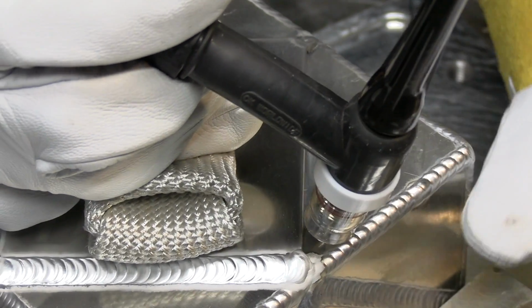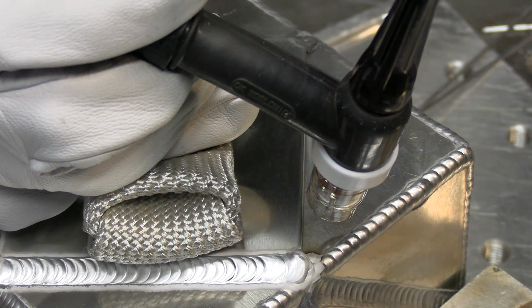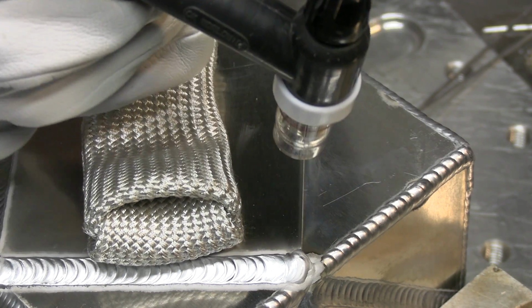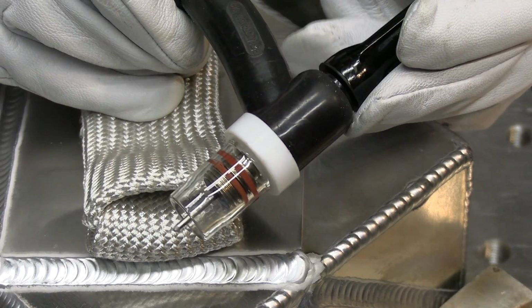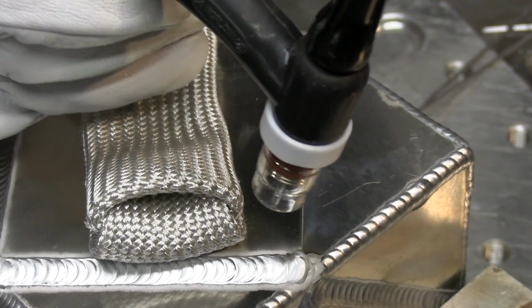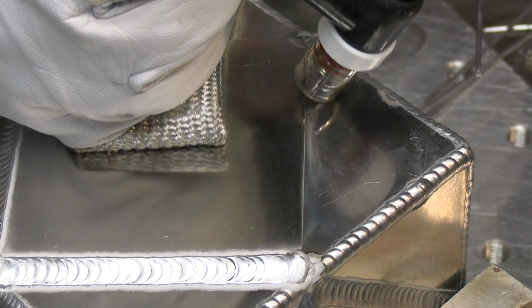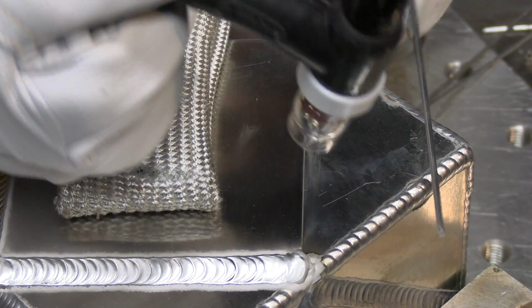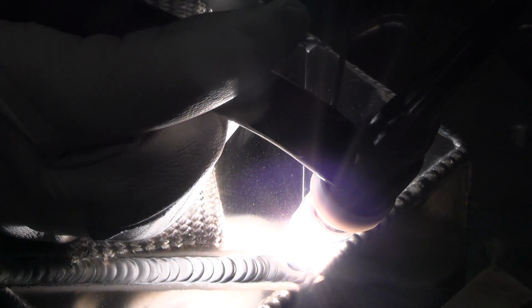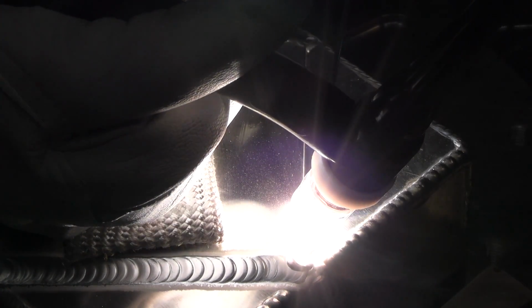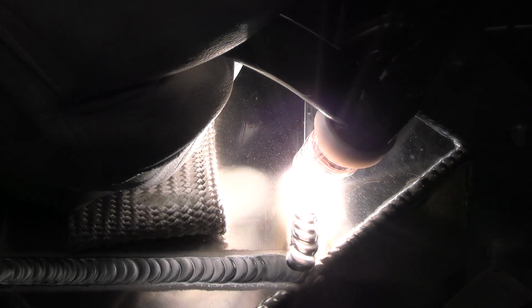Now I'm resting a TIG finger right here on this just to demonstrate what you might do if you're welding on something that you can't spin around on the bench top. Also, a flex head torch helps in a situation like this to get the right angle that you want. Now I've got a different visual perspective on this joint. It looks completely different to me, a different line of sight, and so I'm trying to weld it at the same amperage, but after it was all done I could tell it's a little bit colder, like I probably welded it at about 5 less amps than I did the previous welds.